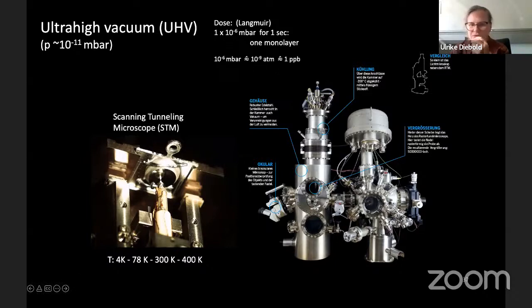So you should take into account, first of all, that this is ultra high vacuum, 10⁻¹¹ millibar. If we have a pressure of 10⁻⁶ millibar in our ultra high vacuum chambers, which is really pretty low pressure, and everything that's in there sticks on a sample because, let's say, it's cold, then that means our sample will be covered in one monolayer in 1 second. Okay, so 10⁻⁶ is not much, right? It's 10⁻⁹ atmosphere, 1 ppb. So that's where we do it.